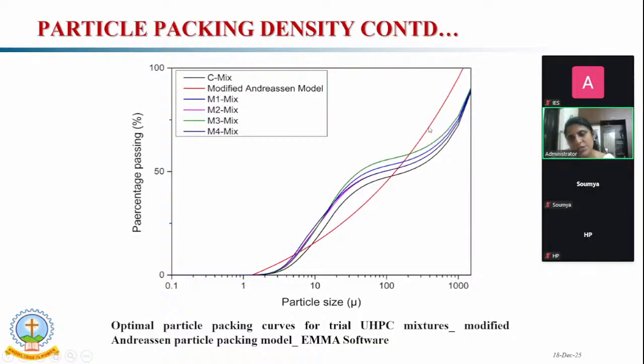These gaps show that some sizes of particles are missing here. In some cases we can increase the quantity of particles of that size, or in some cases we can reduce the quantity of that size of particles, in order to fit the curve to the modified Andreasen model. So what we have done is, firstly we considered the MAA model, then we considered many trial mixes and put them into the MAA curve and checked the graph. Then we modified the mix design by considering this graph.